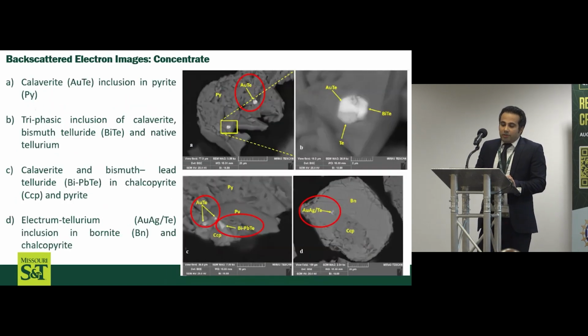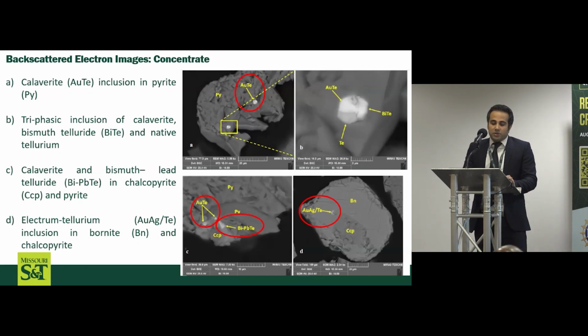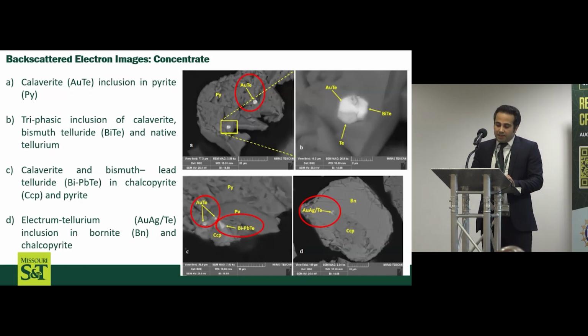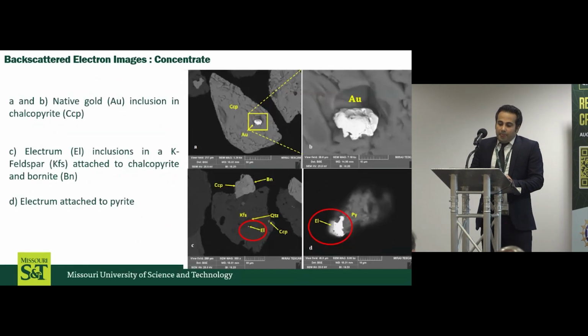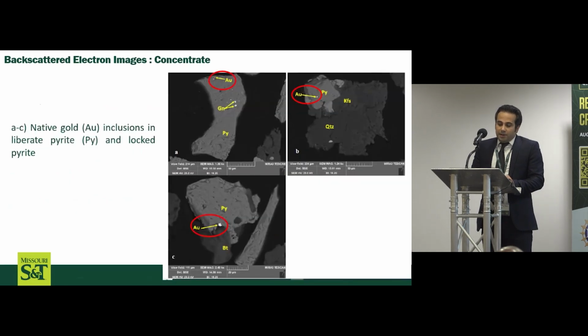You can also see the calaverite inclusion in pyrite, a very interesting three-phasic inclusion of calaverite, bismuth telluride, and native tellurium in pyrite, and several tellurium minerals like calaverite and bismuth lead telluride in the other backscattered images. You can see native gold inclusion in chalcopyrite, electrum inclusion in potassium feldspar, and electrum attached to pyrite. Last but not least, native gold inclusions in liberated pyrite and locked pyrite were found.